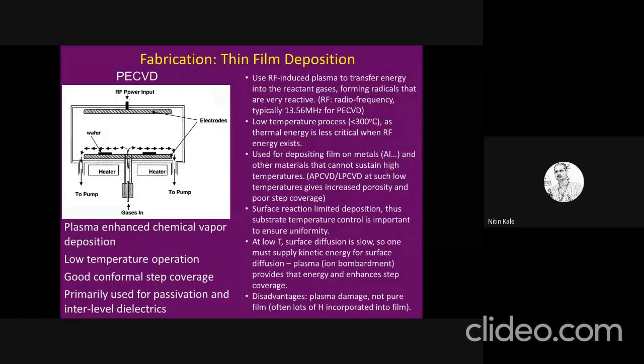There is another technique which is called plasma enhanced chemical vapor deposition. In this technique, instead of using temperature to dissociate the gases, we use plasma. That's all. So you will have two plates, a high voltage across it, RF or DC, depending on what you want to deposit. And then you can create a plasma, and let's say from ammonia you get nitrogen, from silane you get silicon, and both are going to react, combine and form silicon nitride, and that's going to be deposited on the wafer. It will get deposited elsewhere also, but it deposits on the wafer as well.